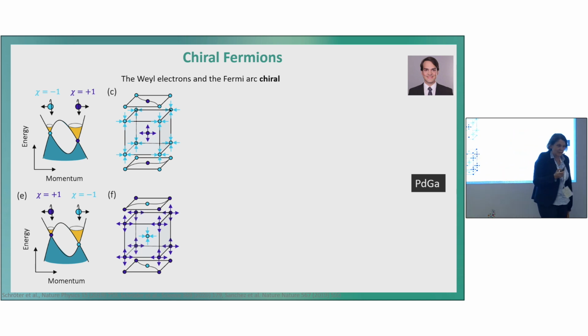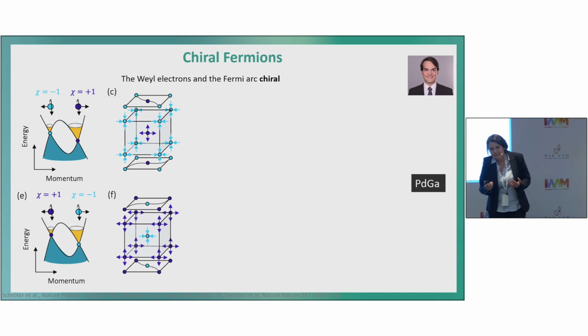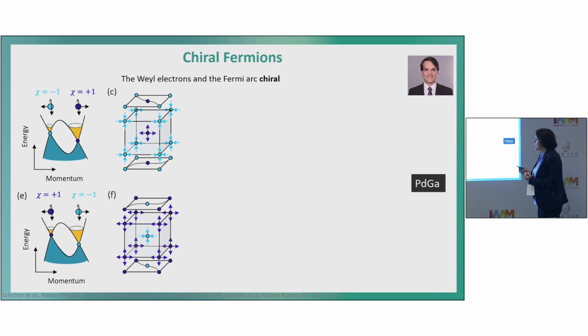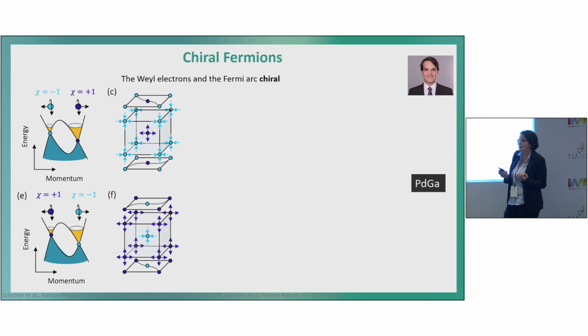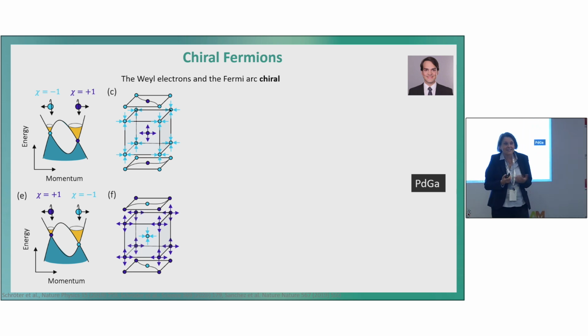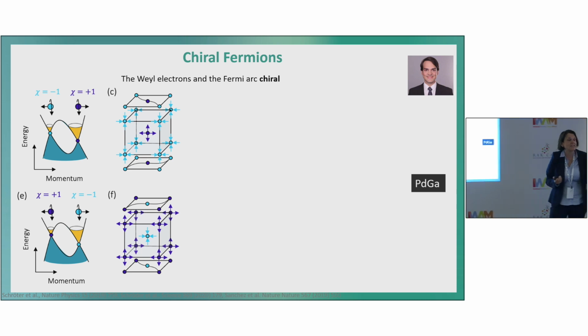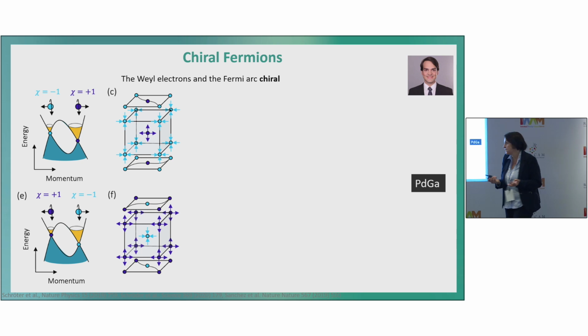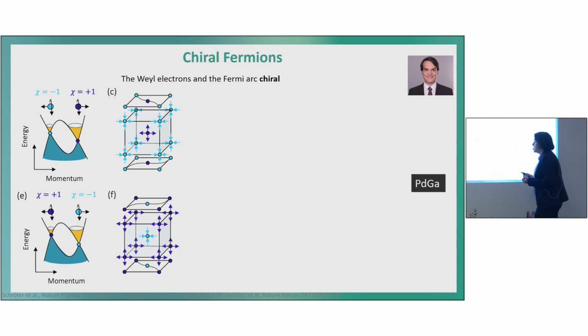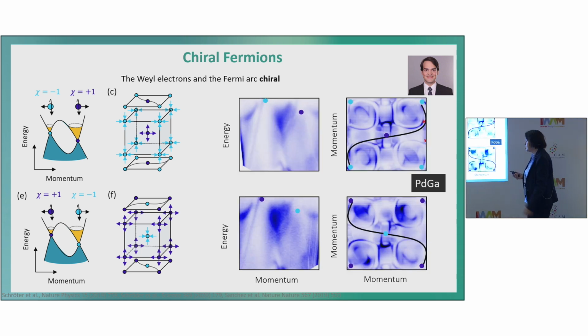But this leads to another interesting property. Not only does what we call the Berry phase have different signs, but also the surface states are chiral. This was surprising for me, and I didn't find anything before about chiral surface states, but it's even in trivial materials that the surface states are chiral. I checked it for the non-topological insulator iron silicide, and it's the same. And indeed, this is what we see.